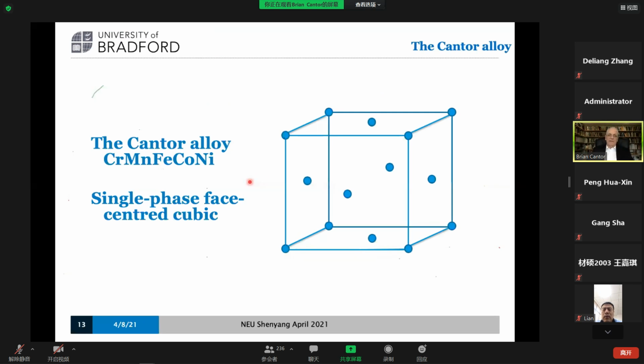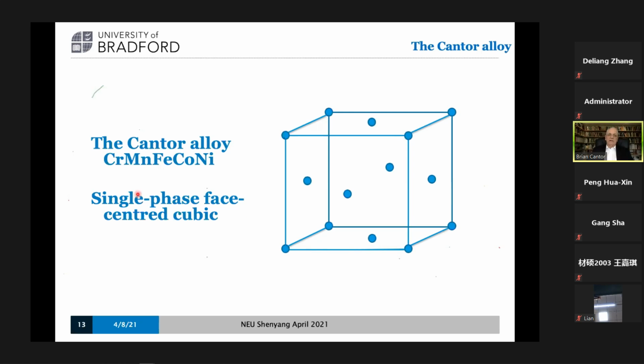I apologize. So that material is the Cantor alloy, as it says up here. The Cantor alloy, which consists of chromium, manganese, iron, cobalt, and nickel in equal proportions, 20% each. And it turned out to be single phase, face-centered cubic. And this was a big surprise. And of those 5 components, only 1 is face-centered cubic at room temperature, nickel. The others are not.